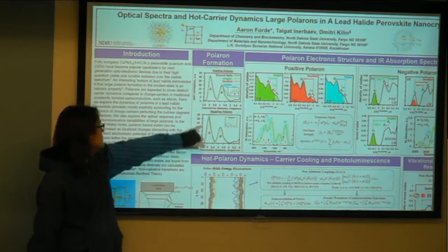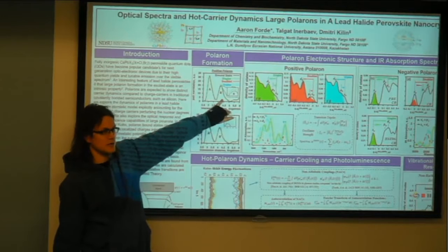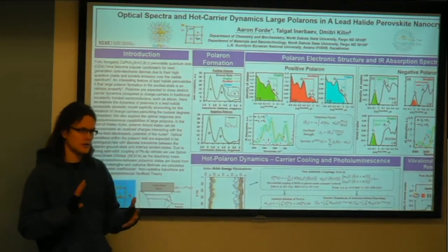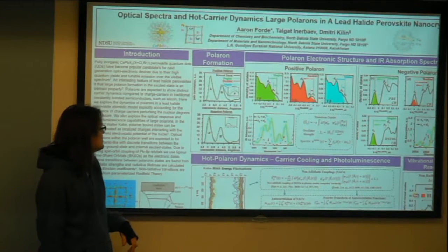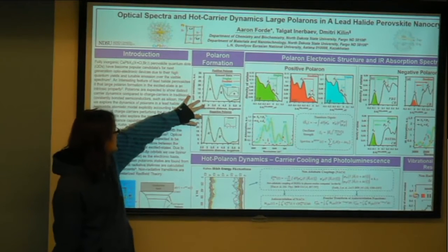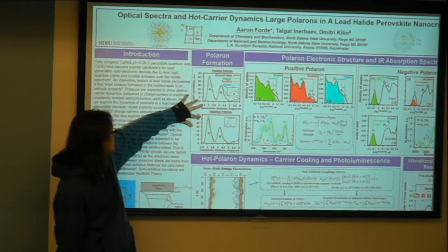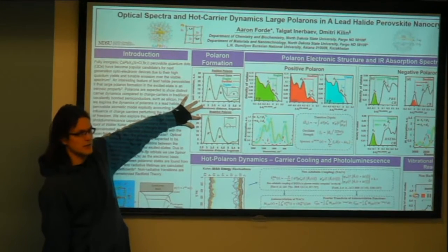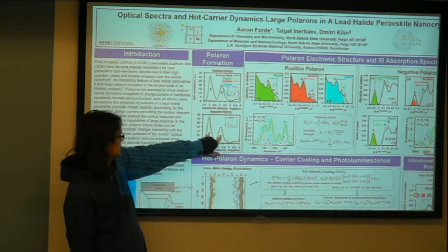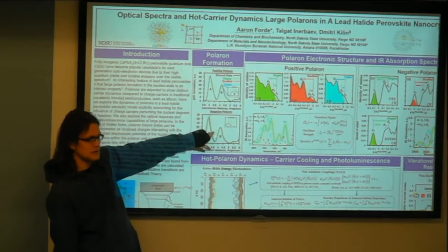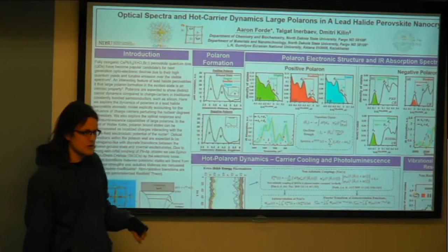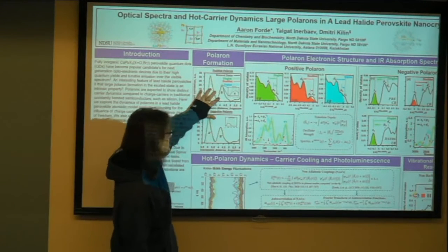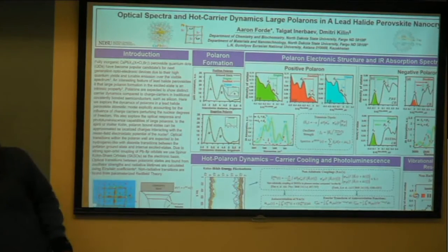repel a little bit. And then you can do the same rationalization where if you put in a hole, the bromines become less negatively charged, so they have less interaction with each other. And just to preface, if you include positive and negative into the same model, you see two different types of reactions from both of them, which we'll get to eventually. So these are changes in the nuclear coordinates.